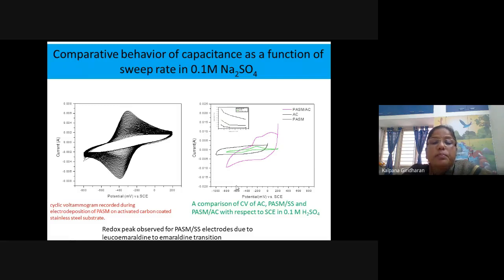This is a typical CV plot at a sweep rate in 0.1 molar sodium sulfate solution, recorded during the electrode deposition of polyaniline on activated carbon coated stainless steel substrate. The right side figure is the comparison of CV curves: the black one is activated carbon, the rose color is polyaniline with activated carbon, and the green one is polyaniline alone.